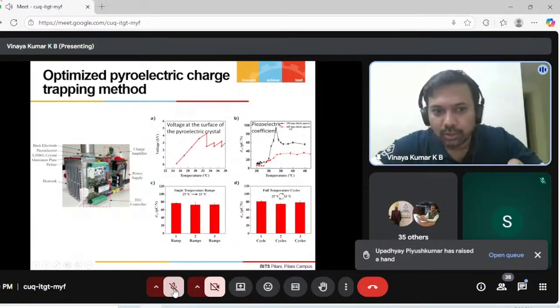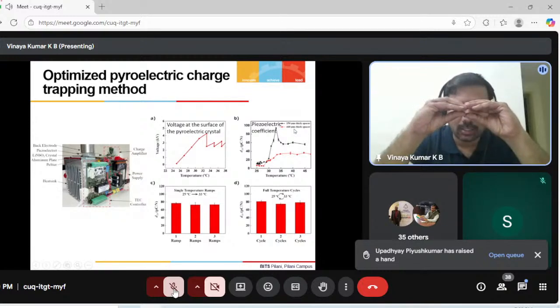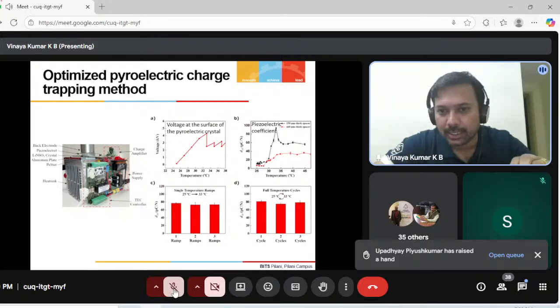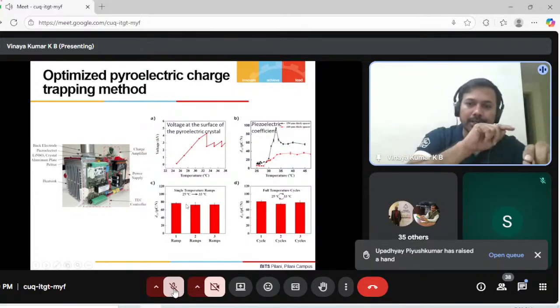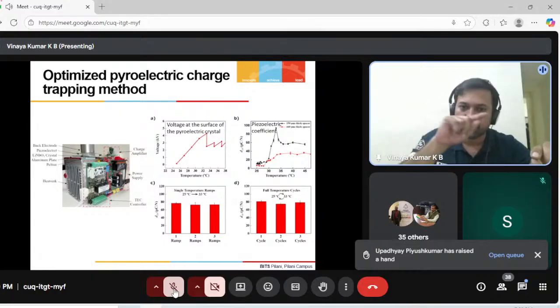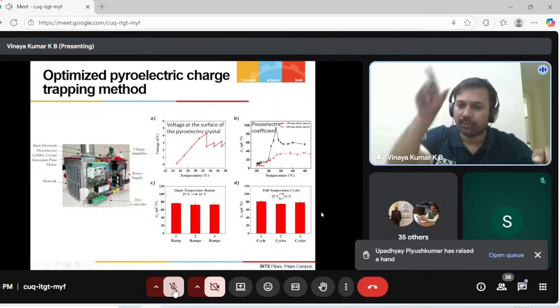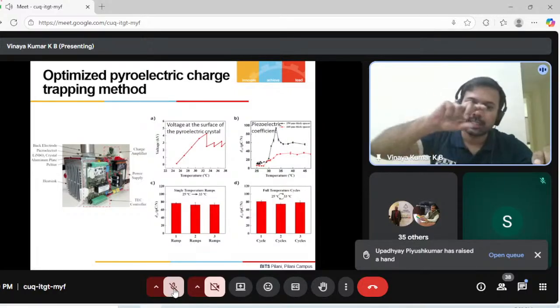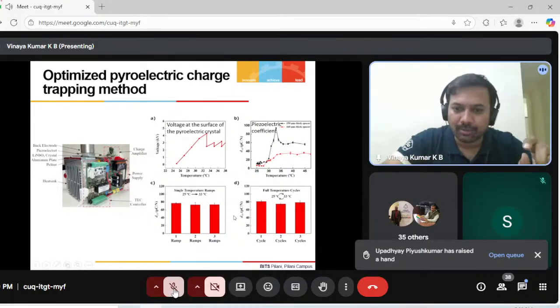Similarly, we also measured it for different thicknesses of the spacer. Like I said, we are making a void, a smaller void and a bigger void, as small as 150 micron void, as big as 440 micron void. Here is the piezoelectric coefficient, the D33 of the measured device in picocoulombs per Newton. Similarly, we also did it for different temperatures. What happens if I do only one temperature in one direction, like 25 to 33 degrees, or if I do a full cycle, from 25 to 33 and also the other way around? Does it affect anything on the D33 parameter we measured? So there's not much difference.